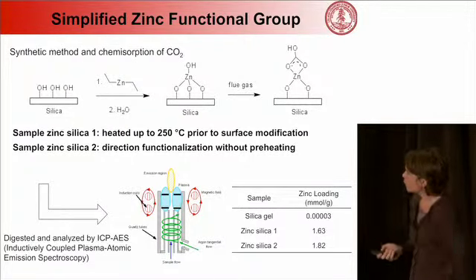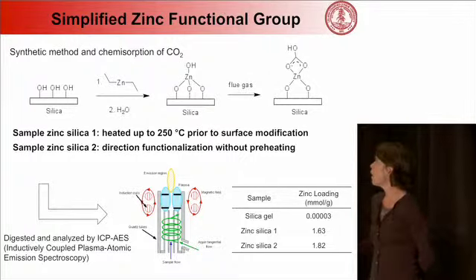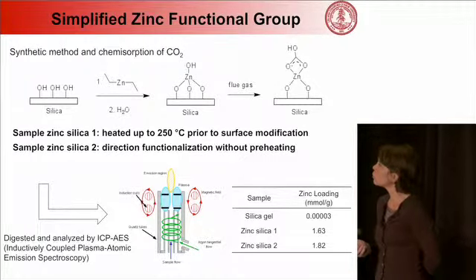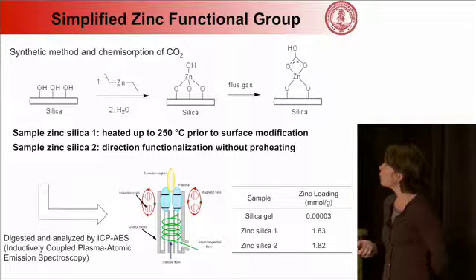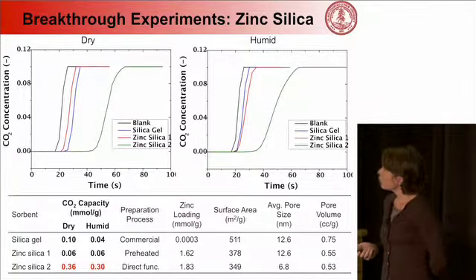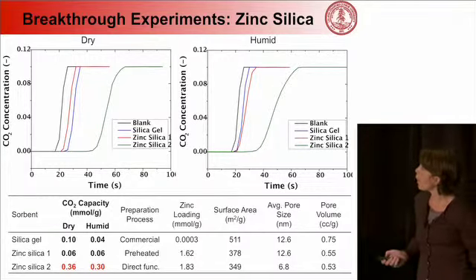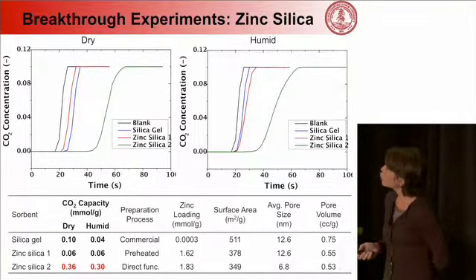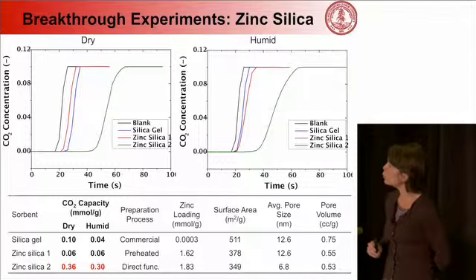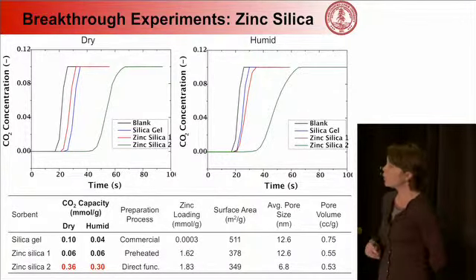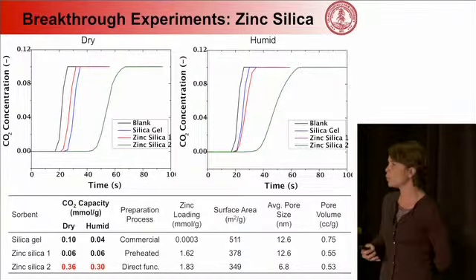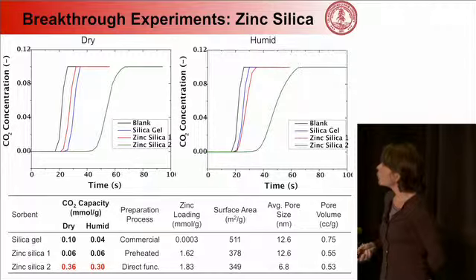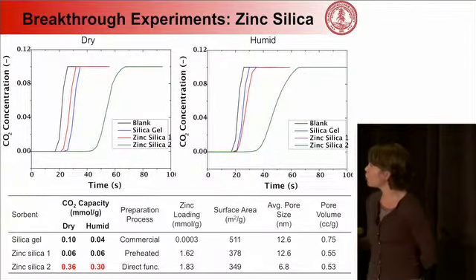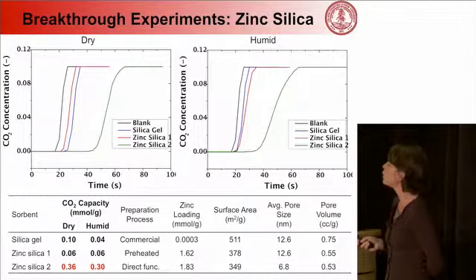And so what we did is take these simple silica-based substrates that have OH groups on the surface of the pores, and then we functionalized them with zinc, and then we used atomic emission spectroscopy to get an understanding of what that zinc loading was on the surface. And so this is an example of the breakthrough curves that we've gotten. On the far left, you see the dry. In that case, you don't have any water vapor in the flue gas. And on the right are the humid conditions in which we're testing more realistic flue gas, because we're including water vapor. And then what you can see down below is the table showing the CO2 capacity as a function of dry versus humid conditions.